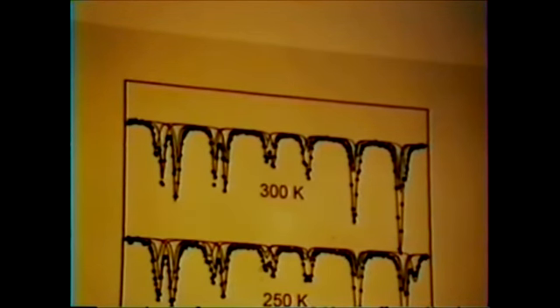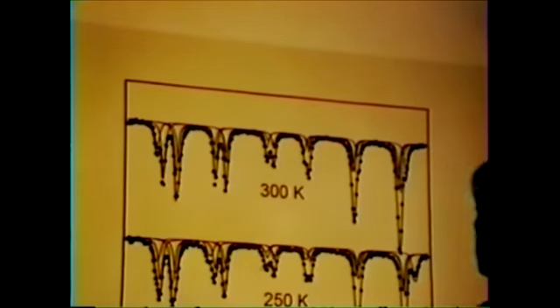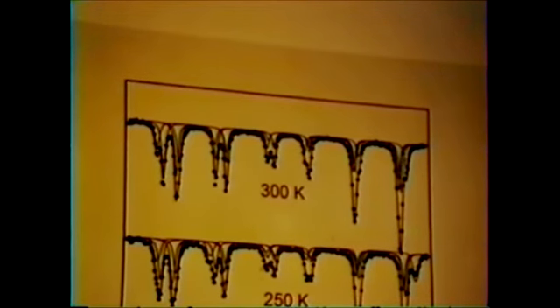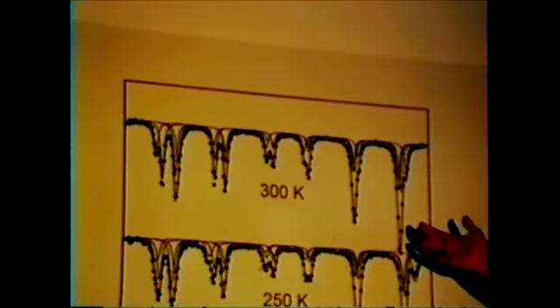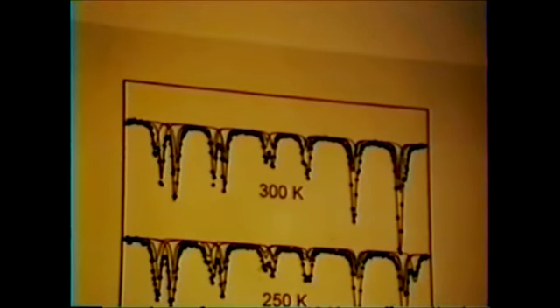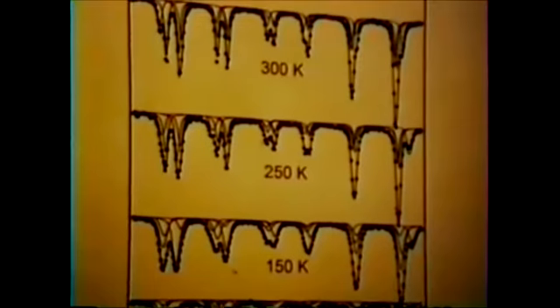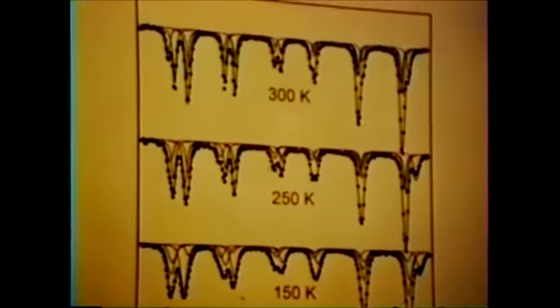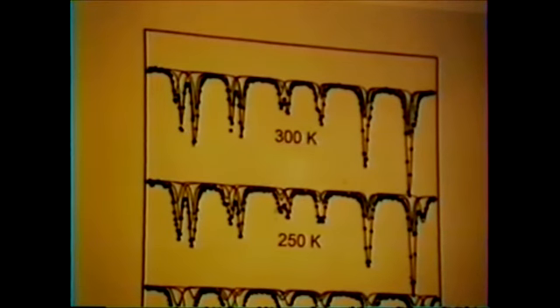Now, what produces this is the stoichiometry. Like I said, the material is non-stoichiometric, and people did see it before. However, probably due to advanced Mossbauer spectroscopy or because this material is high purity, we were able to resolve this extra one, and we've seen it. And then the discovery of this one led to new information about the electrical conductivity in this material. Now, if this is ascribed to the B site, it was postulated by Verwey that on the B site, because you have equivalent sites, the electron is hopping between iron 3 plus and iron 2 plus, so you have mixed valency, a valence of iron 2.5 plus, and that's what the nucleus sees.